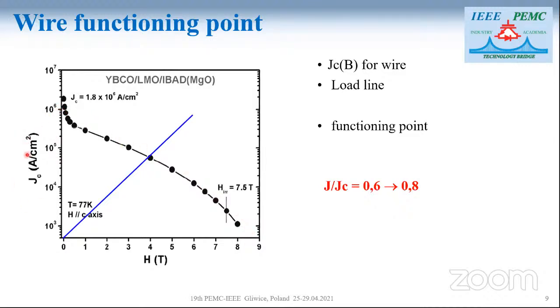You have Jc, the current density, and the magnetic field. And you can see here the load of the application. So we have on one side the characteristic of the superconducting wire for a given temperature, and on the other side, the load line for the application. And we first define the operating point, the functioning point. So it's not exactly like a copper coil. You really need to work with the behavior with magnetic fields of your superconducting tape, and it's different for each kind of superconducting tape.